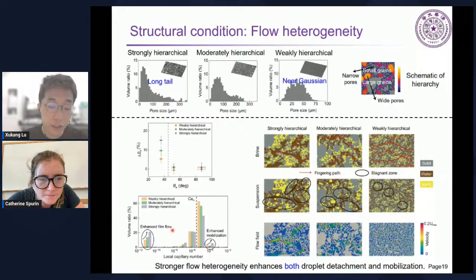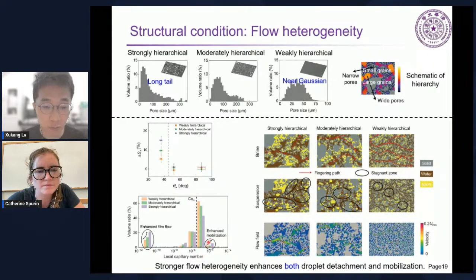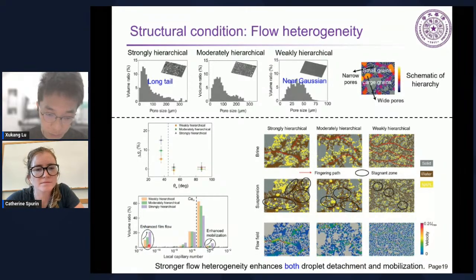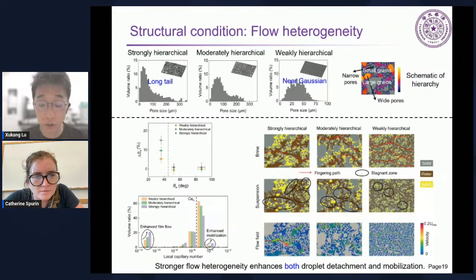Yeah. Actually, so here we define a local capillary number. Because of time, I didn't go into the details. So basically, we just extracted the pore network from the porous media we have generated, and we just calculate a single phase flow field to extract the characteristic velocity. And then at each pore threshold, we can calculate the local capillary number. And the reason we have these extremely low capillary numbers is that we have these stagnant zones. So basically there is nearly no flow there. So because of those flow heterogeneity.